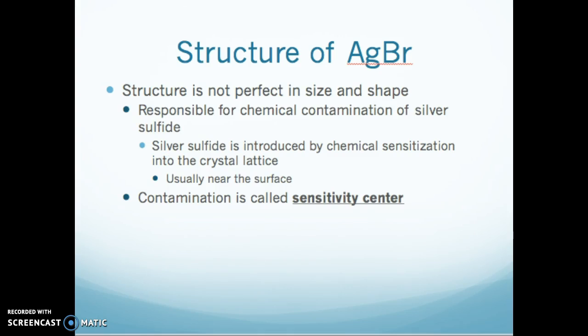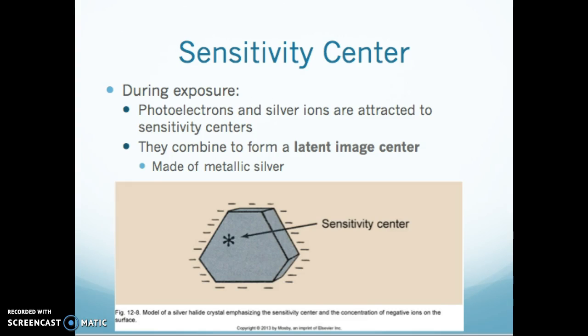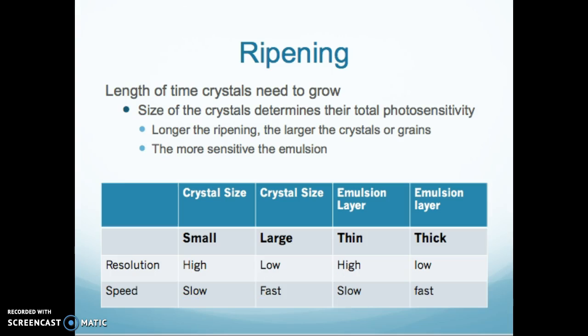Your structure of silver bromide is not perfect in size and shape. It's responsible for chemical contamination of silver sulfide. The silver sulfide is introduced by chemical sensitization into the lattice. It's usually near the surface, and we call that the sensitivity center. Photoelectrons and silver ions are attracted to these sensitivity centers, and they form the latent image center. That's where your metallic silver will be seen when you process.